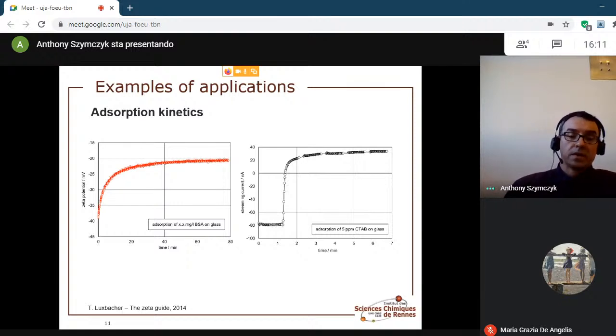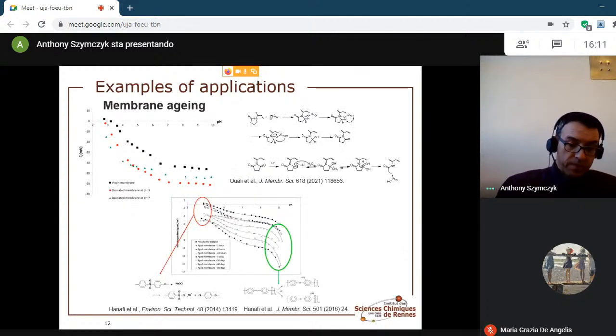Since the zeta potential includes both the effects of the surface charge and of the species adsorbed onto the surface, monitoring the temporal evolution of zeta potential can make it possible to study the adsorption kinetics of fouling species. Another application of great practical interest in membrane science is the detection of membrane aging under the action of various chemical agents. Depending on the type of physical-chemical changes suffered by the membrane surface, this may result in a change in the amplitude of the electrokinetic curves or a shift of the isoelectric points, or also a change in the shape of the electrokinetic curves.